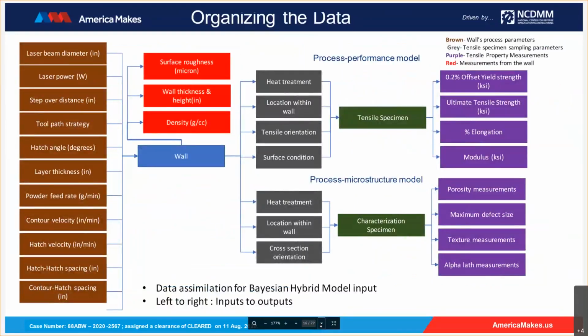Right. So now to structure all the data and capture all the context in the specimen sampling and testing, we had to organize the data starting from the left to the right. The left includes the different variables relevant to the building process. At post building, you attain the wall, which is a component, and there you can get surface roughness, physical measurements, and density. From that stage, the component can undergo heat treatment as post-processing. And if you're doing tensile testing, you can sample specimens from different locations and orientations and surface conditions, following which the specimens can be tested to obtain mechanical performance.